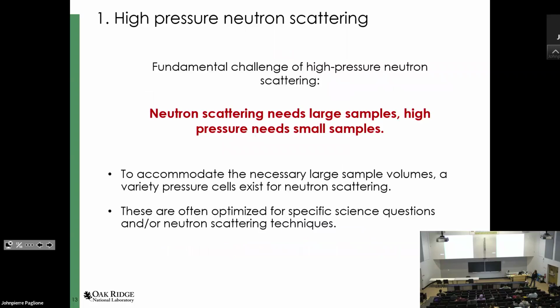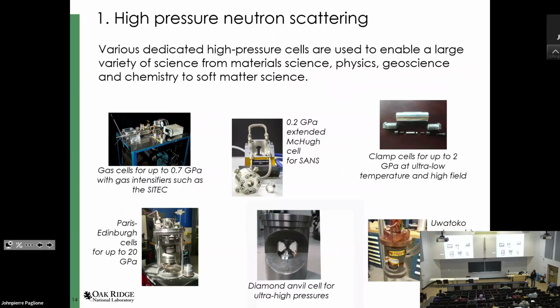And the result of that is that we still use a large range of different cells that are specific to a given application. So just to give you a quick overview, the typical cells that are used in high-pressure neutron scattering are gas pressure cells. So these are cylindrical cells where a gas intensifier drives in a gas up to 10 kilobar. Actually, at NIST, they can do 10 kilobar. We can only do 7 kilobar.